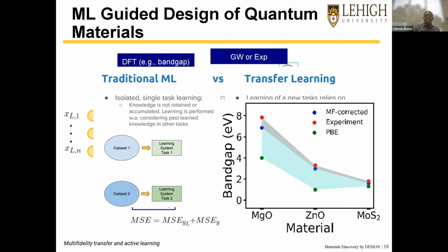What I'm showing you here is a typical example of a transfer learning approach where we can improve the PBE data. PBE is Perdew-Burke-Ernzerhof, which is a semi-local functional within density functional theory. As you can see, these are the band gaps that it predicted. For MgO, ZnO here, I just took a diversity of materials that have large, small, and intermediate band gaps to show the trend. Then the red one is the experimental data.